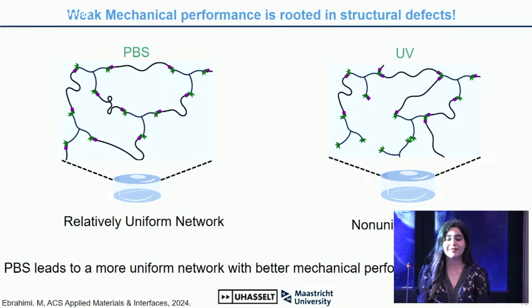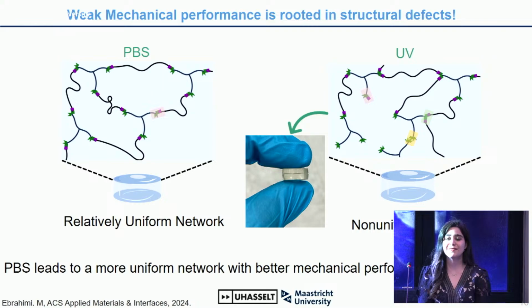As I mentioned earlier, weak mechanical performance is rooted in structural defects. During gelation in PBS, reaction between thiol and alkyne functionalities is the most viable reaction pathway, leading to a more uniform network and better mechanics. On the other hand, several competing reactions can occur in the UV-cured thiol-ene hydrogels, which reduces the mechanical integrity and also homogeneity of the structure. These defects or inhomogeneities can act as stress concentration zones, leading to premature